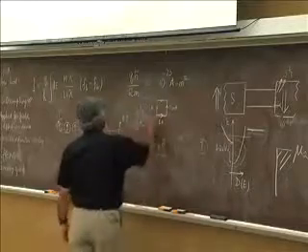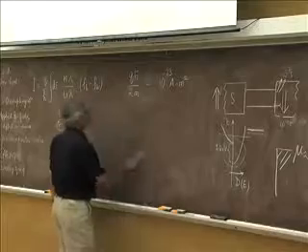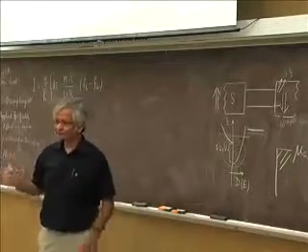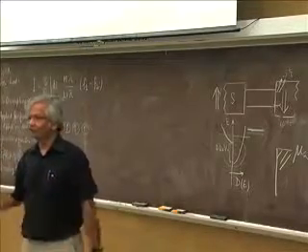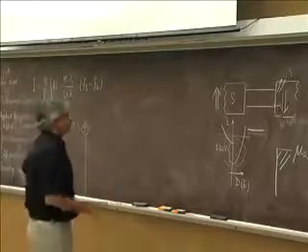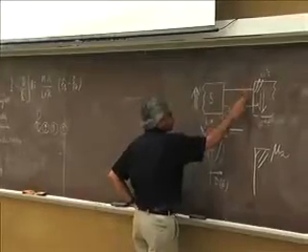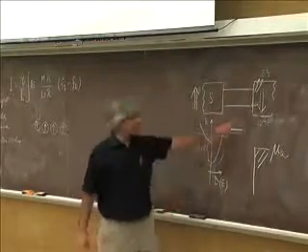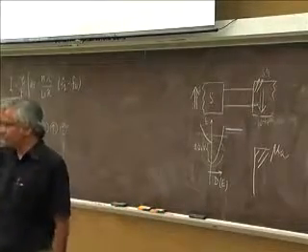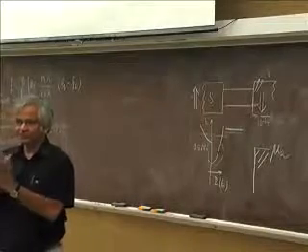But even then, there are many people who say that if you just see a magnetoresistance, that's not convincing enough proof that you have these effects that we are talking about. You should look for something like the Hanle effect or things like that. Because they say that just the fact that you have a magnet there means you will be having all kinds of fringing fields, and if the resistance changes a little bit when you turn it, who knows, it might be some complicated Hall effect because of the field that changed, etc., right? Especially if you're talking of a fraction of a percent, a very small thing.